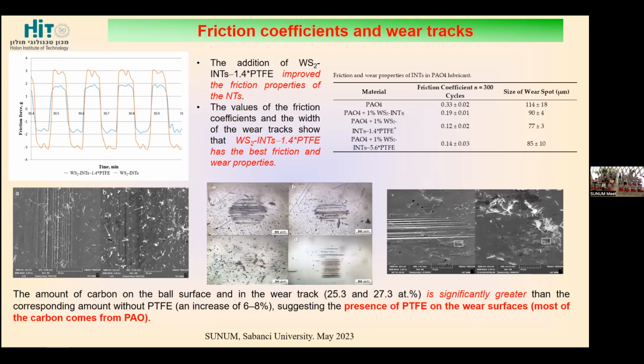Then we measured the friction coefficient under different standard experiments, with a standard method. The friction coefficient of these nanoparticles went down with the increase of Teflon concentration. PAO is a kind of polyolefin oil which is used for friction experiments. The nanotubes added to this oil and coated with Teflon decreased the friction coefficient several times, to nearly 0.15, which is quite good for this type of materials. After friction, the amount of carbon inside the tracks was significantly greater for these Teflon-coated nanoparticles, which means the stability under friction was quite good.